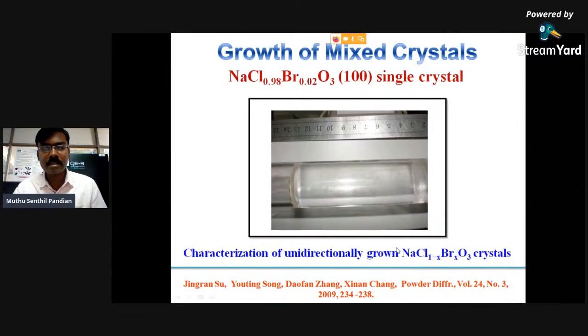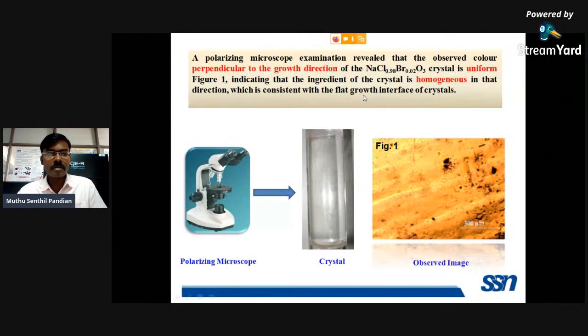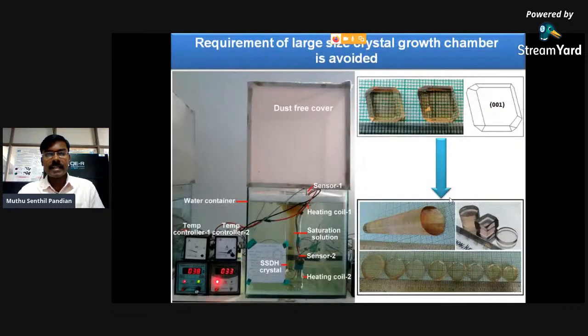This is the growth of mixed crystals reported in a powder XRD journal. These crystals have been grown in one of the Chinese laboratories, sodium chlorate bromate single crystal. They have checked the uniformity of the grown crystal, and this appeared in the journal. A polarization microscope examination revealed that the observed color perpendicular to the growth direction of this sodium chlorate bromate crystal is uniform, indicating that the ingredient of the crystal is homogeneous compared to conventional method grown crystals, which is consistent with a flat growth interface of the crystal. This is reported in one of the Chinese laboratories.